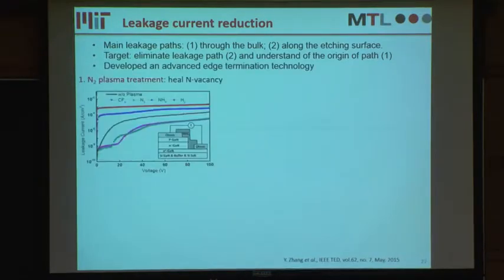The first process we developed is a nitrogen plasma treatment. We found that if we use a nitrogen plasma treatment right after the dry etching of this mesa structure, it can heal the nitrogen vacancies, lowering the leakage current by about 1 order of magnitude.